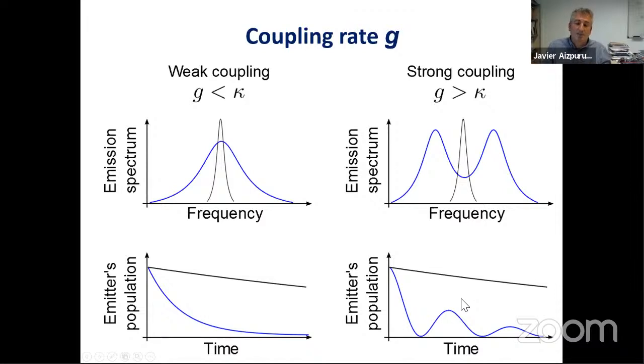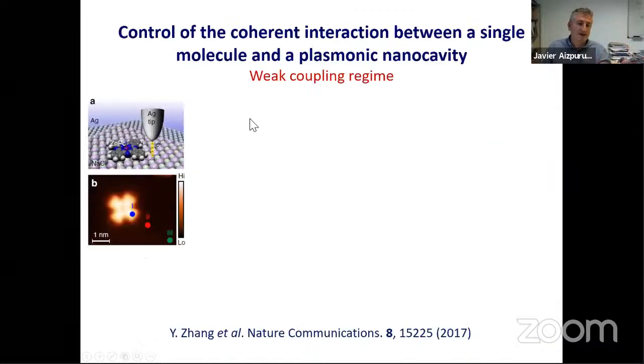In these extreme plasmonic cavities, which boost these g factors, one is again the tunneling junction, this tip on top of the metal substrate. And we put here a zinc phthalocyanine molecule. This is a very good emitter. It's a flat molecule with the dipole aligned in parallel to the surface. And the nice thing about this tunneling plasmonic junction is that you can move the tip, of course, in a scanning probe. And by moving the tip, you move the plasmonic cavity over and scan the molecule, right?